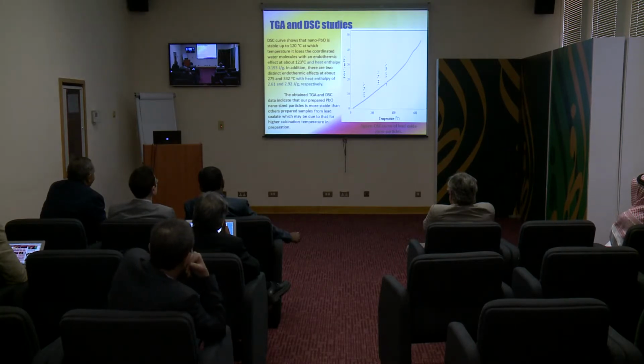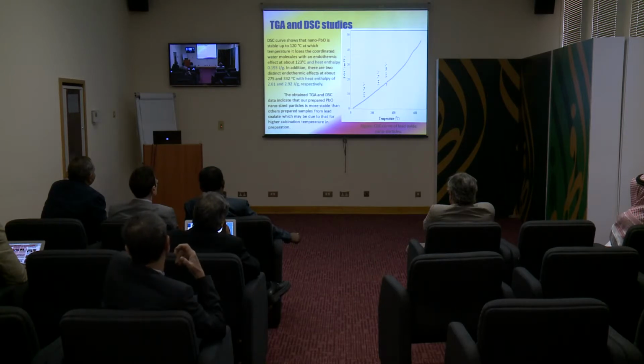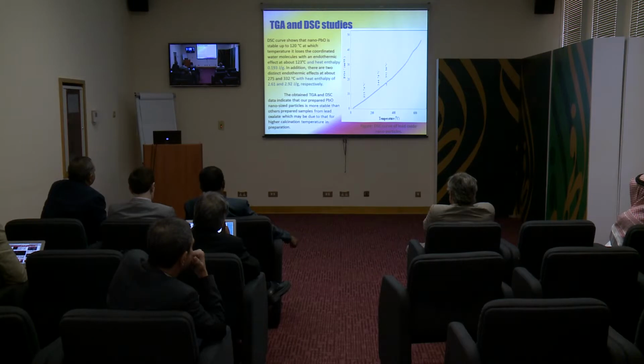The thermal gravimetric and DSC study, as appears in this curve, shows that nano lead oxide is stable up to 120 degrees centigrade, at which temperature it loses the coordinated water molecules.